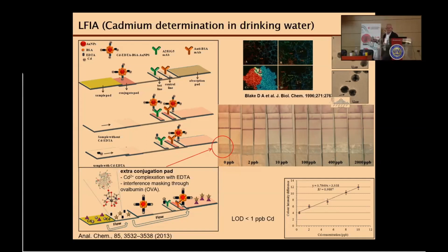the system, this is in fact a competitive system, where you can see we have a very nice response. In fact, here is the contrary, so the less cadmium you have, the higher intensity of line you have, because it is competitive. But the nice thing is that we're able to detect up to 0.1 ppb, which is fantastic. So very, very nice with this device that may cost less than $1.